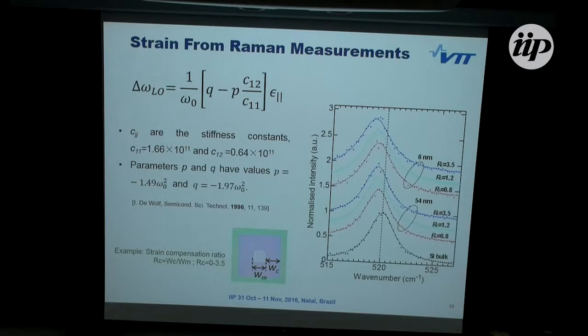And what is the parameter here, this RC? This is just the ratio between this length and this length. So if this WC, or this collar width, is zero, we have this kind of a buckling case. And then when we increase this ratio, the stronger is the strain effect. As you can see, as the RC is increasing, the peak shifts towards the lower number, so it means the strain increases. And when the membrane is thin, the shift is larger. So from this shift, one can get the strain.